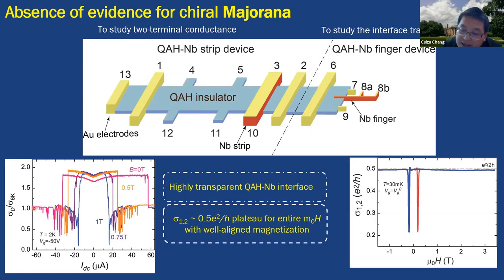We can see here the conductance is enhanced by about 80%. You know, the perfect Andreev reflection is doubled, as it should be. So here is the enhanced 80%. It tells us the transparency between the quantum anomalous Hall and the superconducting niobium film is good.